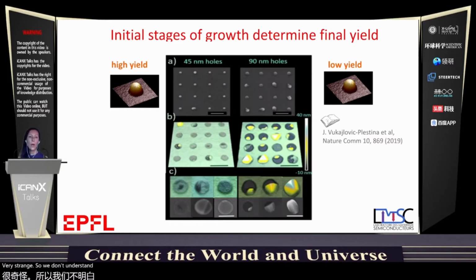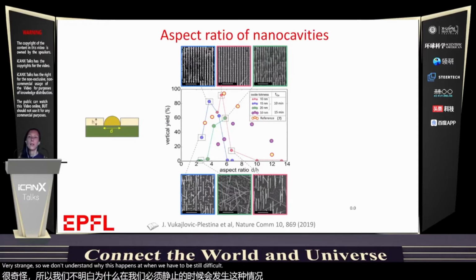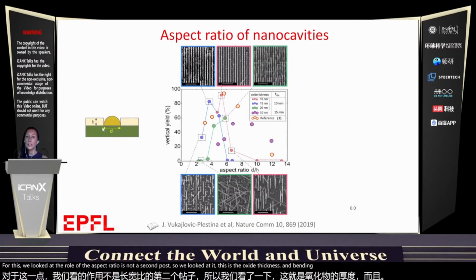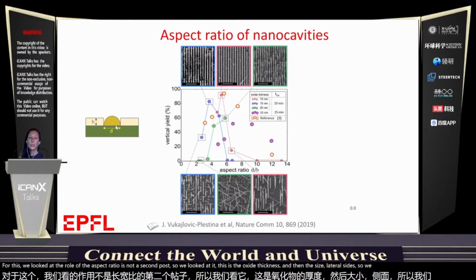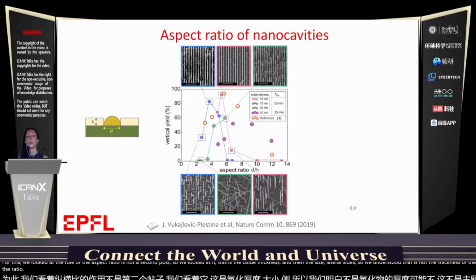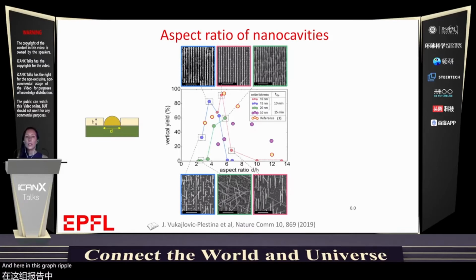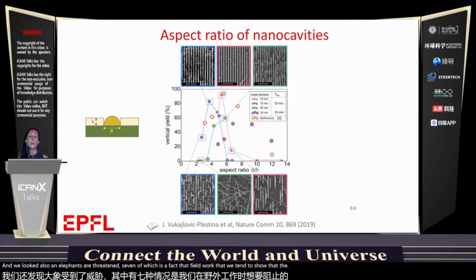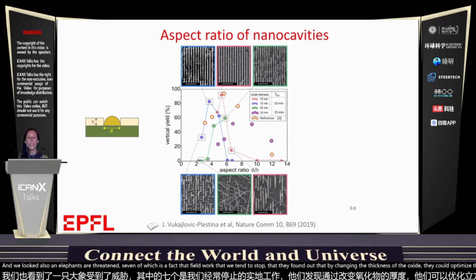So we tried to understand why this happens and when we have this tilted growth. For this, we looked at the role of the aspect ratio of these nanoscale holes. This is the oxide thickness and then the lateral size. So we understood that it's not the thickness of the oxide, it's not the size of the hole, it's the ratio between the two. And here in this graph, we compare the vertical yield for different aspect ratios of this hole. And we looked also at reference 7, which is a clear work, in which they found out that by changing the thickness of the oxide, they could optimize the yield. And in that case, it's because they always get the same size of the hole.